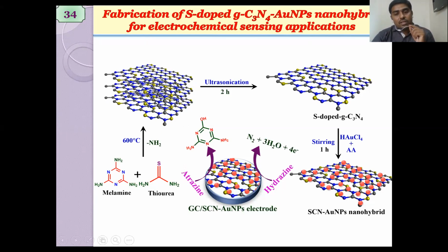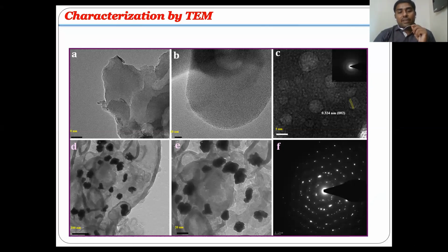After ultrasonication, we get a single layer of sulfur doped graphitic carbon nitride, and the graphitic carbon nitride is employed for the electroless deposition of gold on its surface with the help of HAuCl4 and ascorbic acid, a weak reducing agent, and the gold nanoparticles were fabricated on the sheets of graphitic carbon nitride. The graphitic carbon nitride sheets are very thin layer sheets, and the gold nanoparticles deposition is confirmed from HRTEM images as well as the SAED pattern.